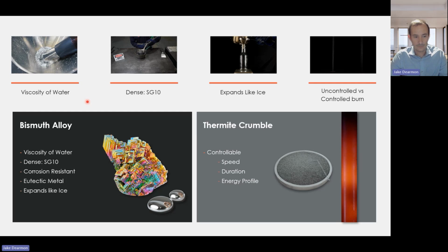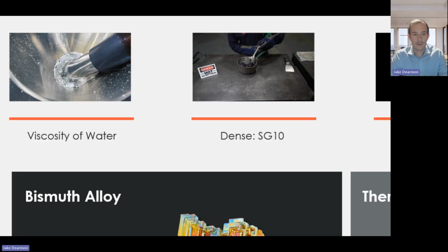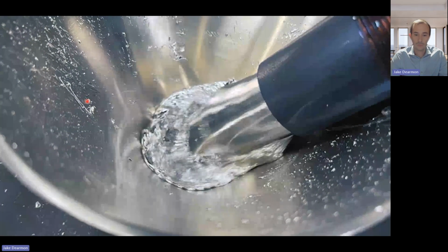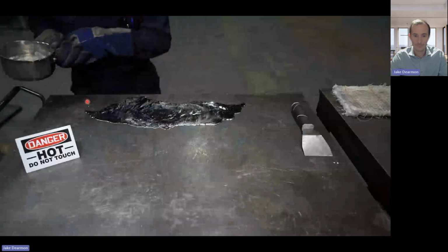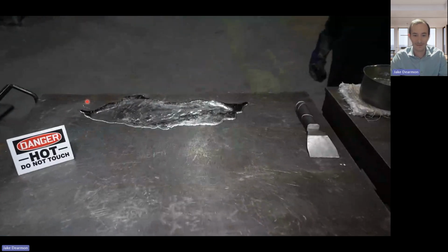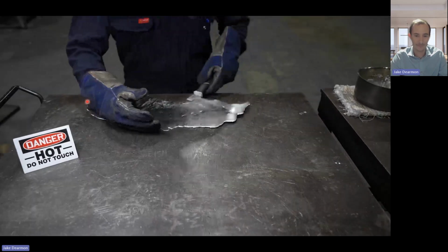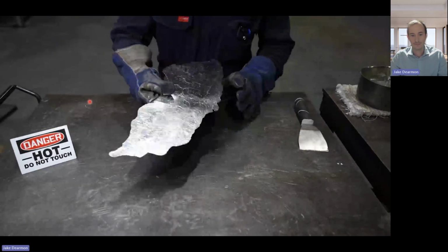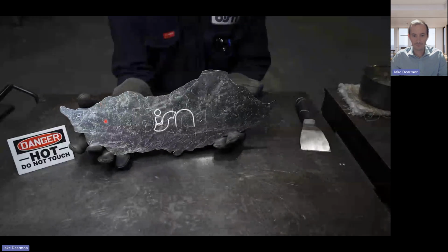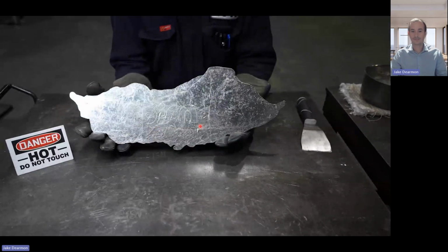Bismuth-based alloys have a few advantages that we use them for at BiSN. The first one is that it has a low viscosity, very similar to water. What we'll see in this video is we're actually pouring that molten alloy into a funnel. Eric here in the alloy department is pouring it on top of a metal table, and when he flips it over, you can actually see all of the imperfections of that table still on the alloy. That's a function of that low viscosity.